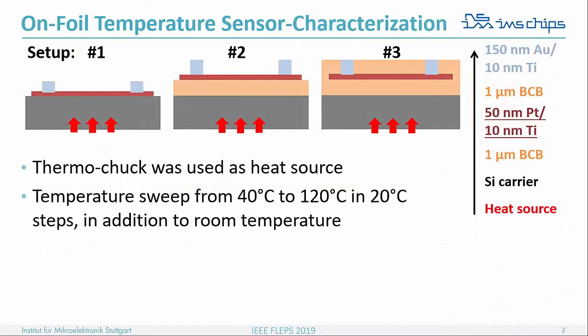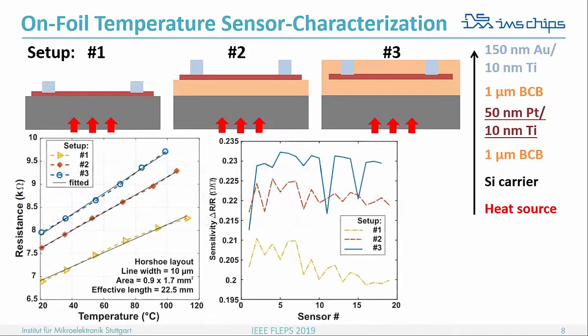So we did some experiments for different construction of the technology. So the PT sensor is directly on the silicon wafer. The PT sensor is on top of the BCB layer, and then the third one is a PT sensor embedded into BCB layers. And then the thermo-chuck temperature was varied to establish the temperature measurements.